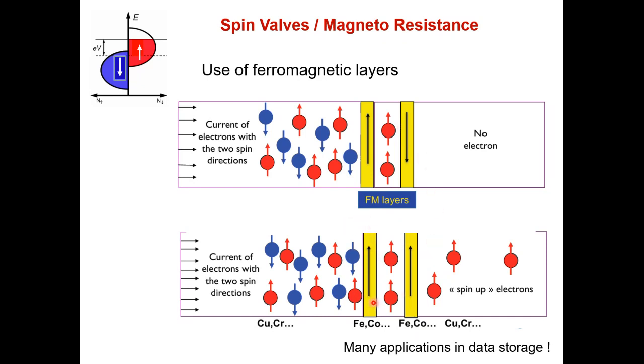Now, if you take two ferromagnets with parallel magnetization, in this case, in the first step, you just inject the spin-up electrons. So you have what we call a spin polarized current. But this current can also cross the second ferromagnet, which is favoring the spin up. And you do have a current flowing across the device. This is called a spin valve. It's a valve that controls the flow of electrons based on the spin of the electron.